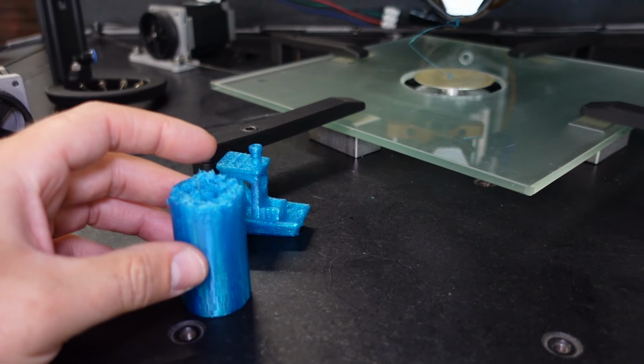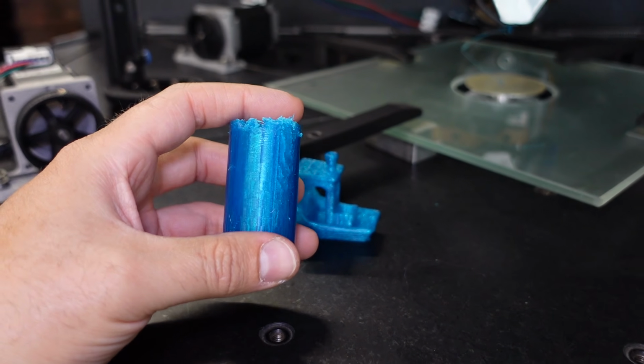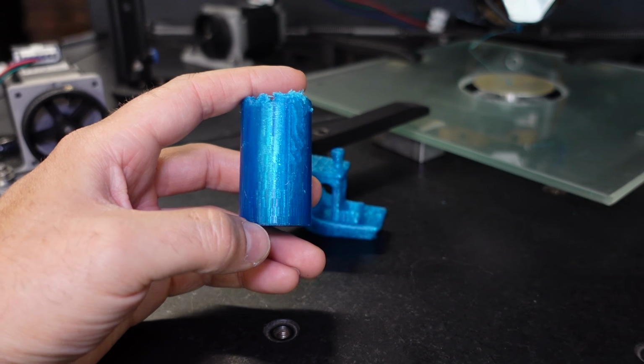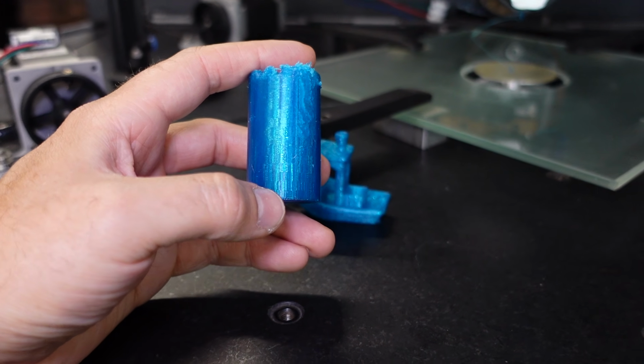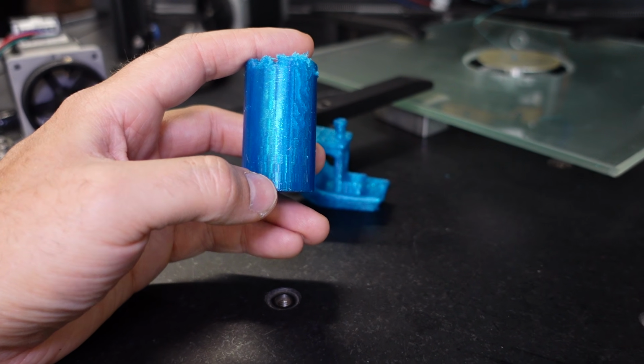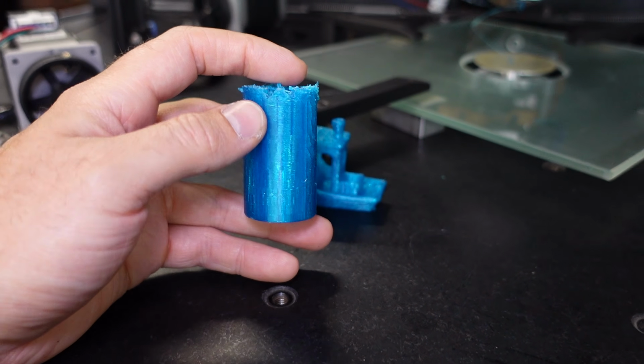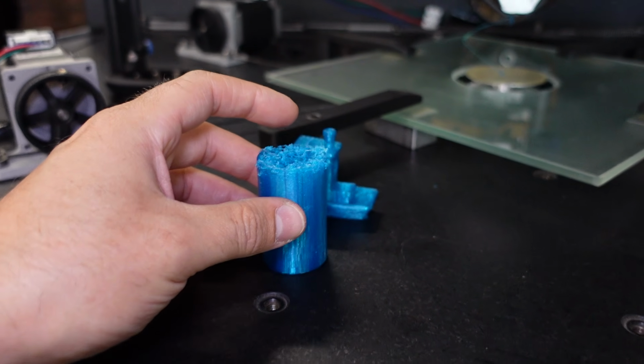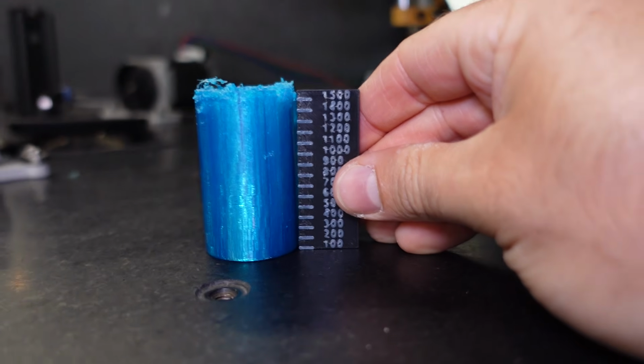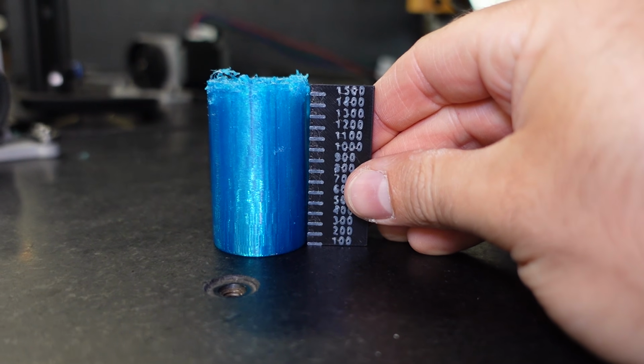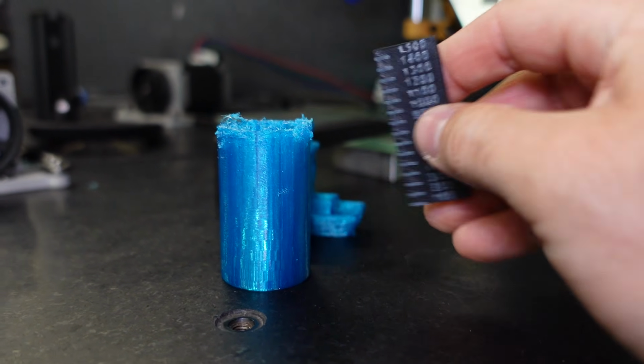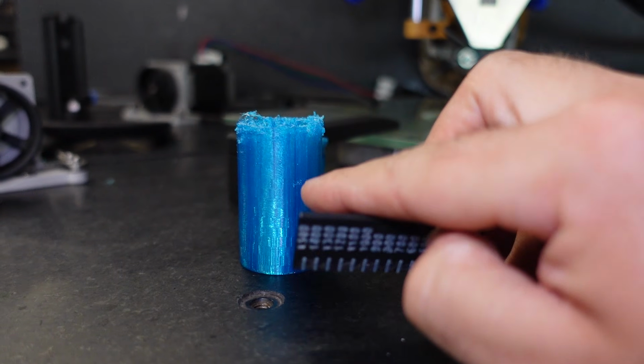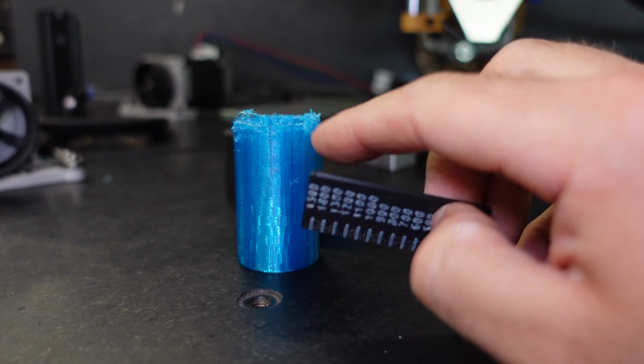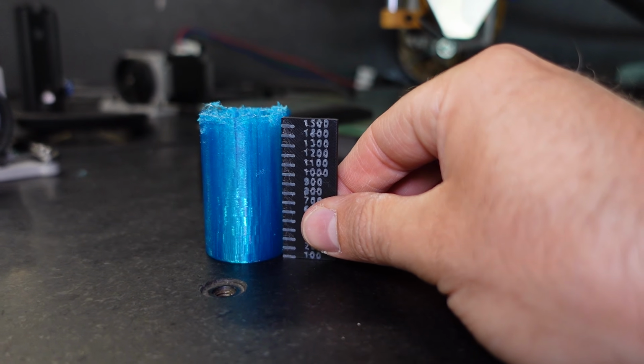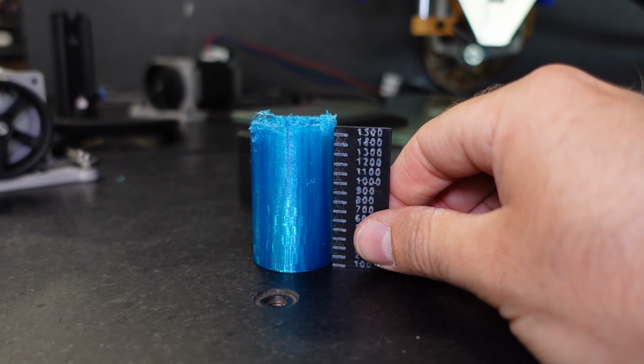The second print I made beforehand is my modified speed tower again. For those that haven't seen that, it starts at 100 millimeters a second right here at the bottom, and then in 15 increments it works its way up to 1500 millimeters per second printing speed. And this is my scale to it. As you can see, with this kind of filament and layer times, this is 6 seconds at the bottom and 0.5 seconds at the top. We managed to print all the way to 1400 millimeters a second, which is quite impressive.